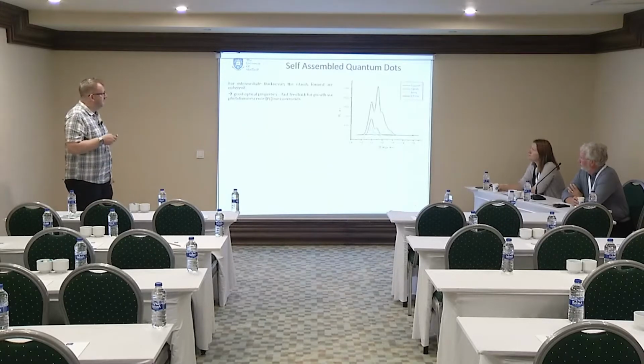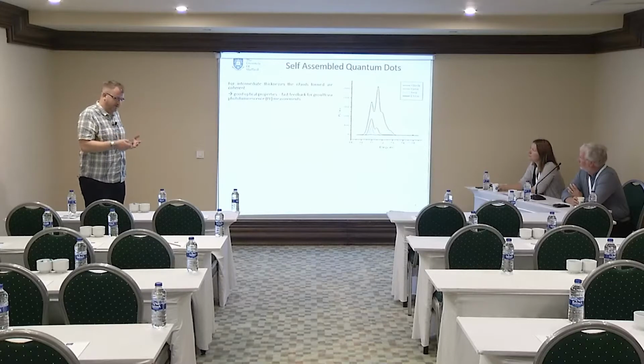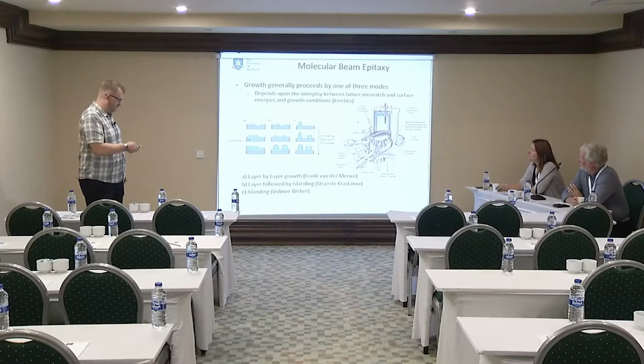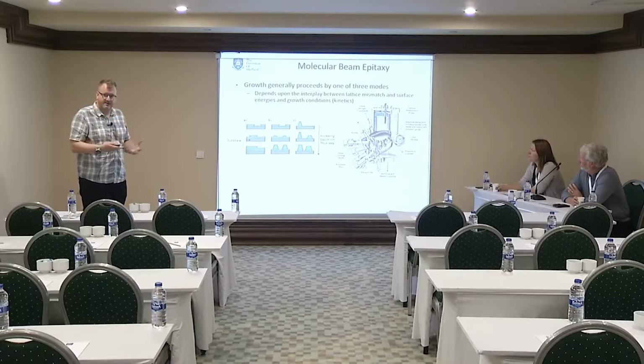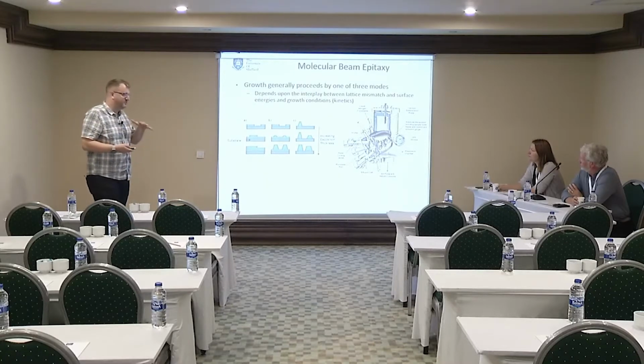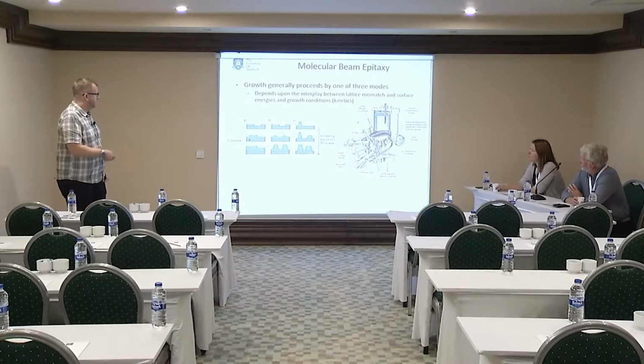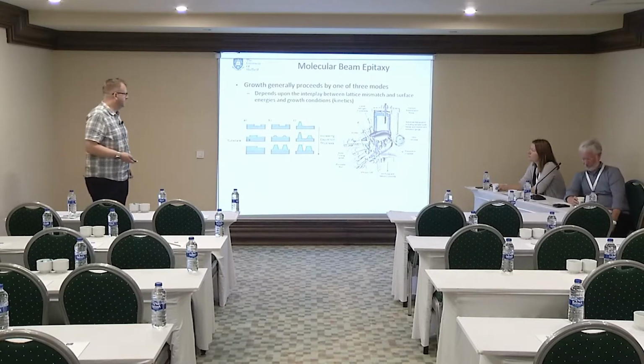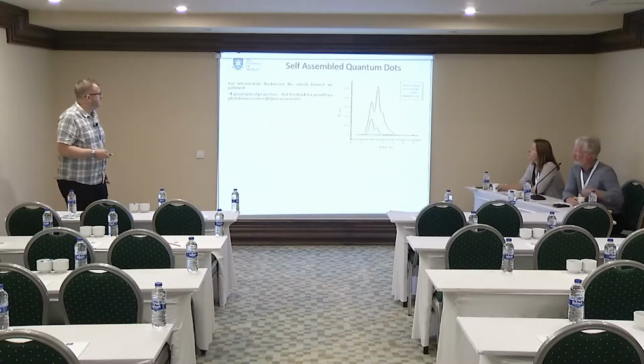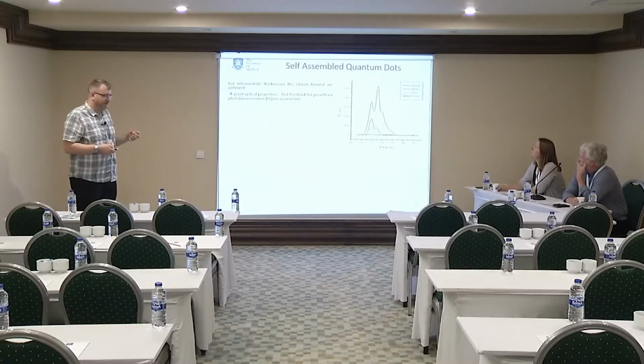The important thing when we look at those films, if I just go back briefly, if I just keep growing, eventually these islands will coalesce and I'll form dislocations. I'll still produce a film. In the first case, I'll produce a nice film, and in the other two I grow quite a thick distance in order to get a smooth surface. But for intermediate thicknesses, the islands formed are actually coherent. So they're a single object, they contain no defects. And that means they have very good optical properties.